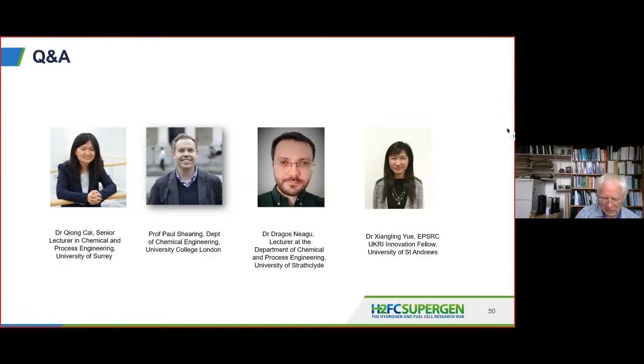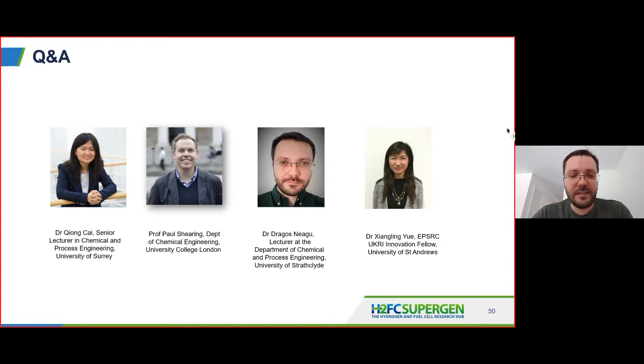Yeah, and perhaps just to add to that, a question about is exsolution just for solid oxide cells, or can it be applied to low temperature fuel cells and electrolyzers? I think definitely. Again, I think we need to play a bit more with the chemistry and ionics of the materials to be able to enable easier diffusion of ions, to be able to trigger this at a bit lower temperatures. But clearly, we've seen that through electrochemical poling, the switching, we can actually go into, let's say, the thermodynamics that would favor exsolution at lower temperatures. So that would be a way.